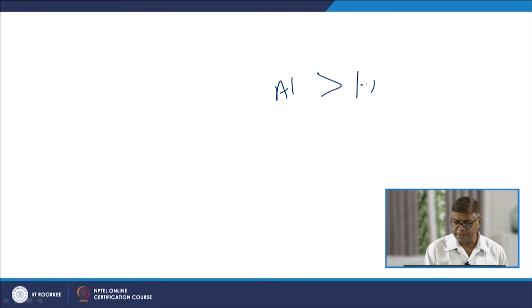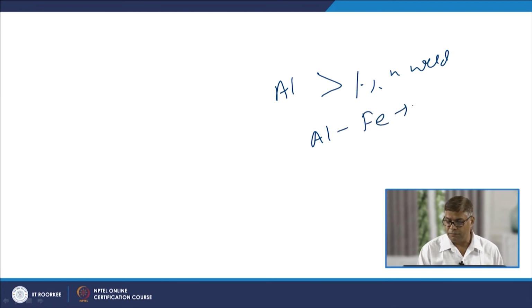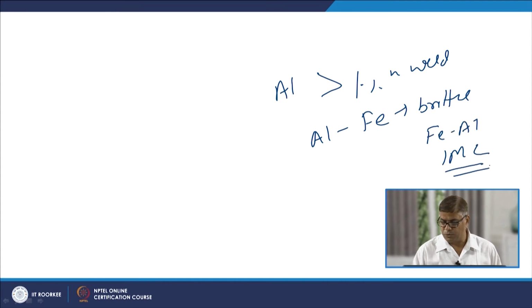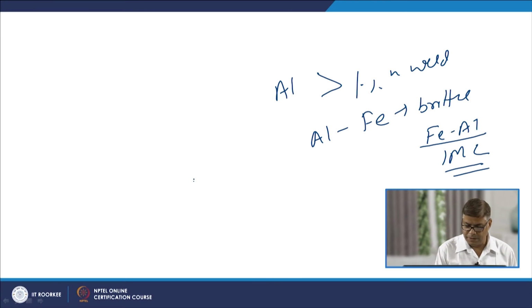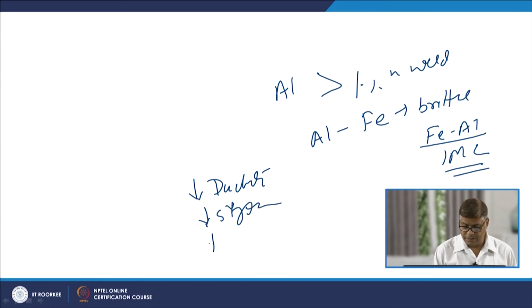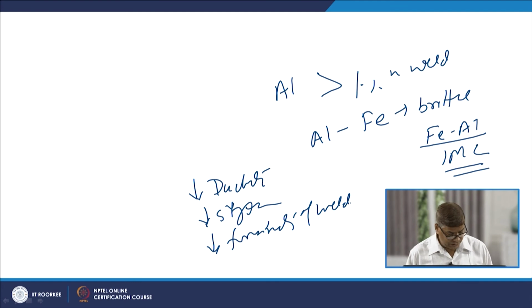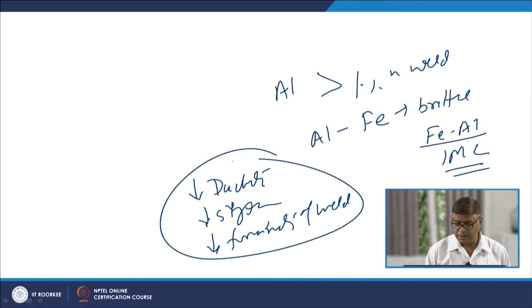A higher concentration of aluminum, greater than 1% in the weld metal, since aluminum does not dissolve in the iron, forms brittle iron aluminum intermetallic compounds. The formation of the brittle aluminum iron intermetallic compounds reduces the ductility, reduces the strength, and reduces the formability of the welded sheets. So, we need to look into this aspect also, like how much aluminum is getting into the weld metal, especially in case of the autogenous welds.